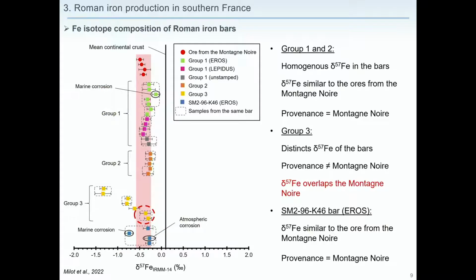So we analyzed the iron-isotope composition of the same bars, and we compare it to materials from the Montagne Noire. So we can find bars from group 1 and 2. First of all, except for the corroded sample here, and maybe not this one, all these bars have a very homogeneous iron-isotope composition, as you can see within the dotted lines for each bar. Then we can find the group 1 and 2, which have composition similar to materials from the Montagne Noire, so we can validate a provenance from this region for these bars. And then we have the third group, with each bar having its own iron-isotope composition, some clearly out of the variation range of the Montagne Noire, so we can validate another provenance, but still unknown so far.